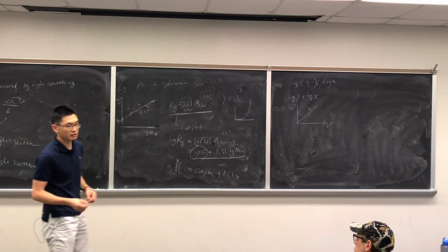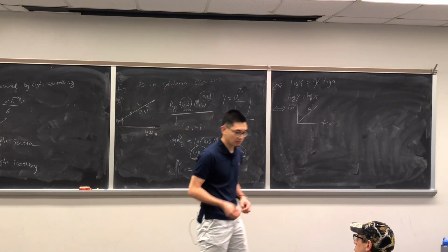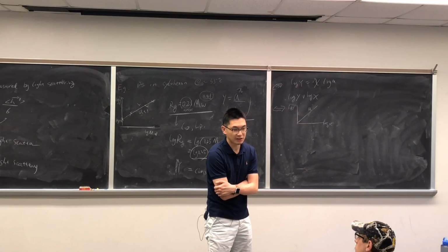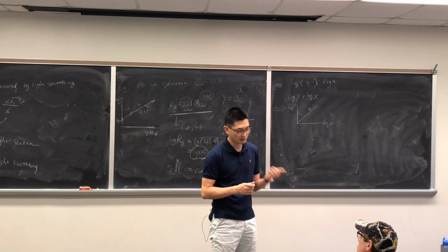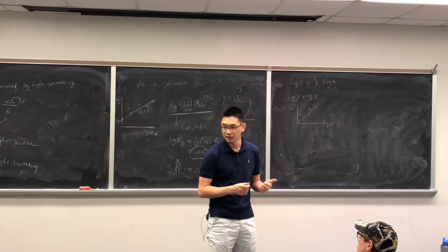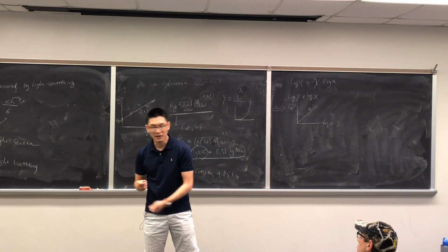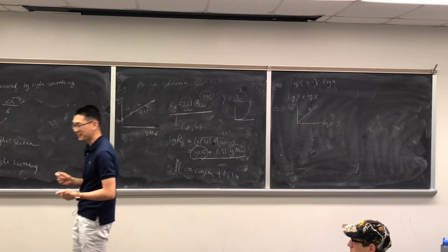It's a little bit out of scope for this class, but you will learn it in the next class. Basically, what light scattering can do is help you understand what the radius of gyration is. That's one parameter. I'm sure Rebecca and Michael have learned this, right? What else can we learn from light scattering? The virial coefficient, the second virial coefficient, right? And there's one more parameter: molecular weight, the absolute molecular weight. That's the intercept of the Zimm plot on the y-axis, right? Good, great.